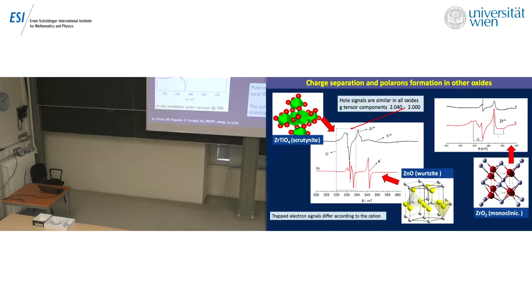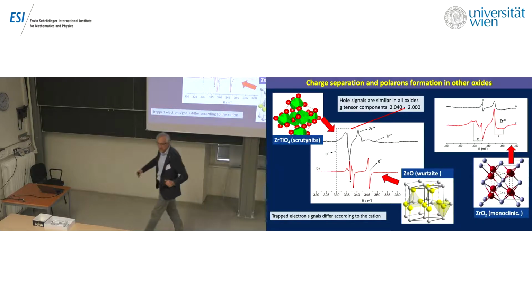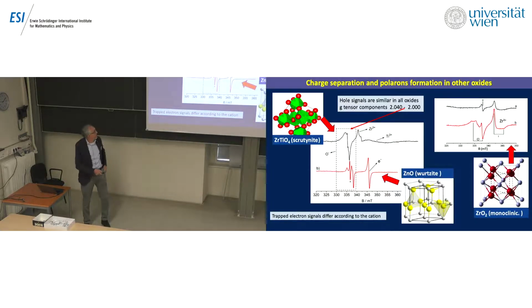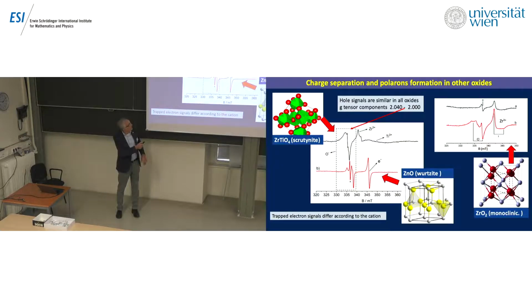And this increases the number of holes that are stabilized, and this can be interesting for people working in photochemistry and photocatalysis. This separation is not just for titanium dioxide. We have recorded this electron-hole separation and charge carrier stabilization in a number of oxides. For instance, this is zirconium dioxide. This is zirconium titanate. This is zinc oxide. As you can see, the hole is stabilized more or less in the same way. There are differences because they depend on the symmetry, but they are in the same region. Quite different is what happens for the electron. There are very asymmetric and broad signals, or very simple signals, like in the case of zinc oxide.